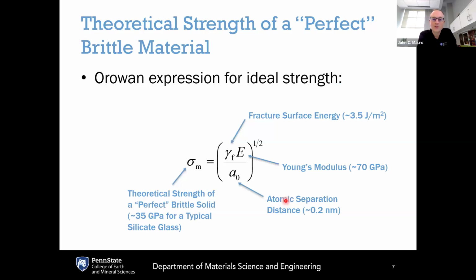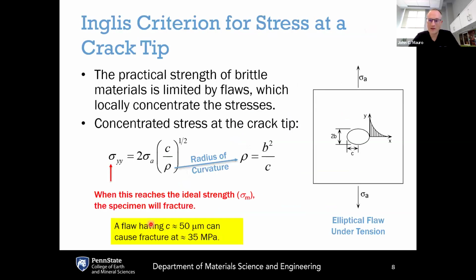Now, if we go back to the original derivation by Orowan of the theoretical strength of a perfect brittle material like glass, this calculation is done based on not having any flaws in the brittle material and just calculating how much energy it would take to break bonds to form new fracture surfaces. And if you put in typical values for a silicate glass, the theoretical strength of this perfect brittle solid would be about 35 gigapascals. So this is much higher even compared to what is observed for freshly drawn glass fiber. What compromises the strength of glass is the presence of flaws. These can be flaws due to the manufacturing process, but more commonly they are flaws due to the handling of the glass products.